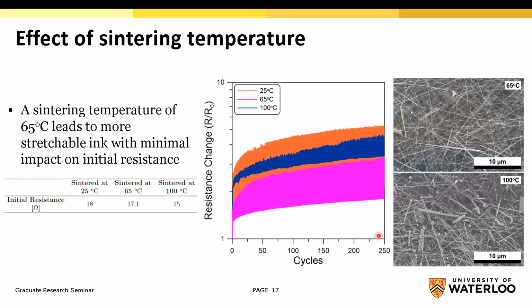And the effect of sintering temperature. For this, we tried 3 different sintering temperatures: 25 degrees, 65, and 100. And you can see the initial resistance of them. Even though the sample sintered at 100 Celsius has slightly better initial resistance than 65 degrees, the sample sintered at 65 degrees had the best stretchability. You can see the magenta is 65.